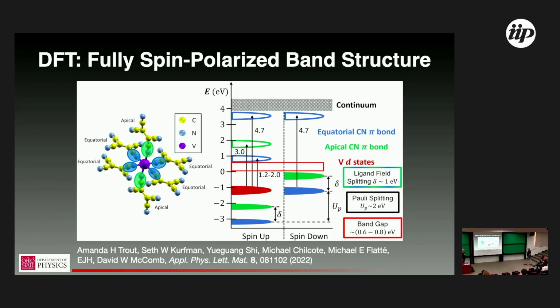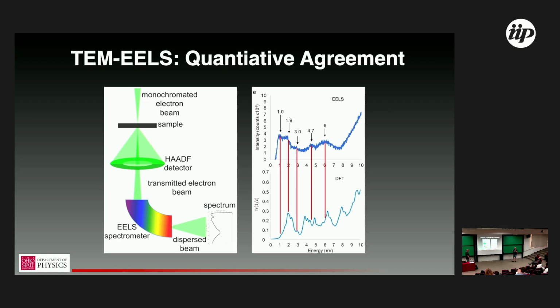And experimentally, can you probe this? Well, for a bit, right? We see resonances at 5 and 6 eV, so we can get into that range. You, in principle, could spin resolve this. So this is electron energy loss. If you did spin resolved electron energy loss, you might be able to see that effect. I think that's a challenging experiment. That's I think a beamline style experiment, but it is potentially possible.